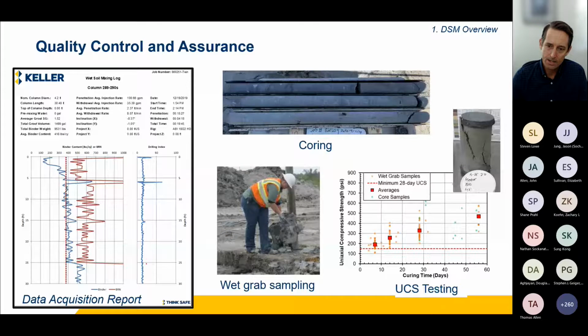And we process that data to give us some critical parameters that are shown on this data acquisition report. On the left side, you have the blue line, which is the binder content. This is the dry weight of cement per cubic yard or per cubic meter that's left in place in the ground. We're typically targeting a value that, based on our experience and maybe a bench scale test, is going to provide the unconfined compressive strength for the design. You can see that the blue line is targeting the dashed black line, which is our target value.